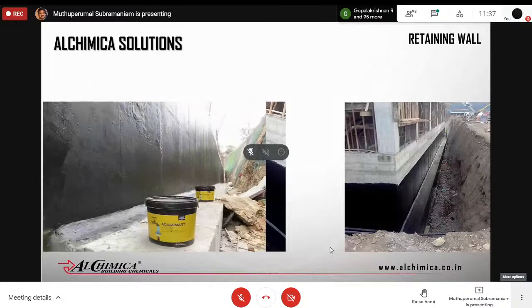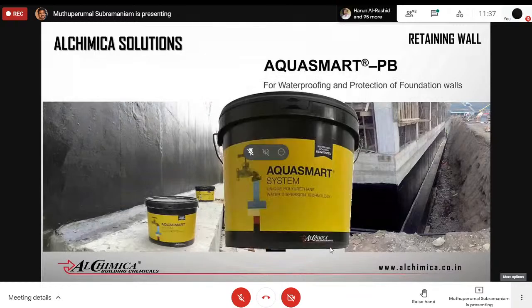So here we are using a product called AquaSmart, which is a water-based polyurethane coating. The first product I referred to for terrace and podium is a solvent-based waterproofing, whereas here it is a water-based polyurethane system. Why do I need a water-based polyurethane system? Because after the retaining wall is done, the structure above the building will continue to progress. They will continue to construct the superstructure, whereas they give the waterproofing treatment operation to the waterproofing contractor. And when the contractor goes to apply the waterproofing coating, certainly there will be spillage of curing water from the superstructure.